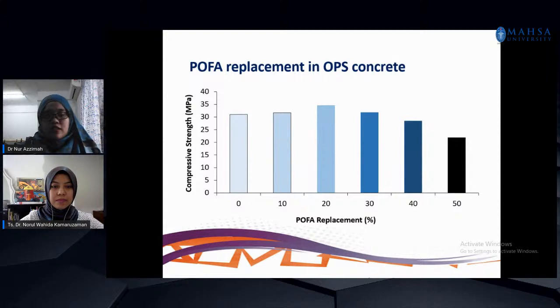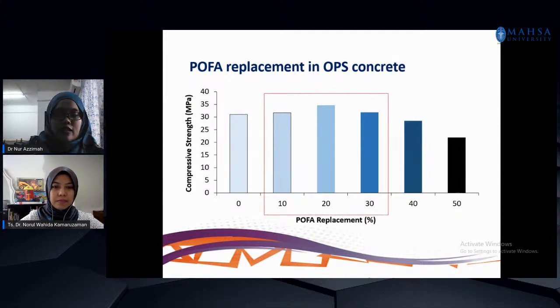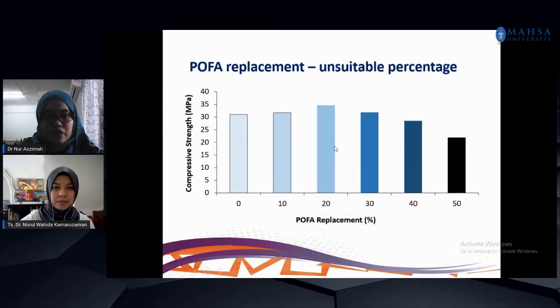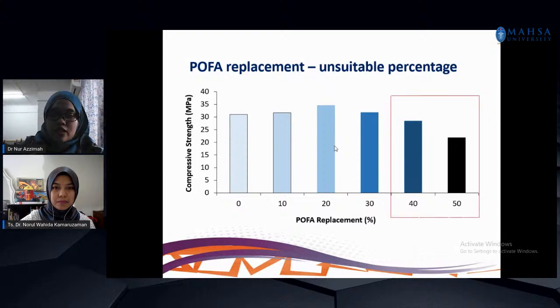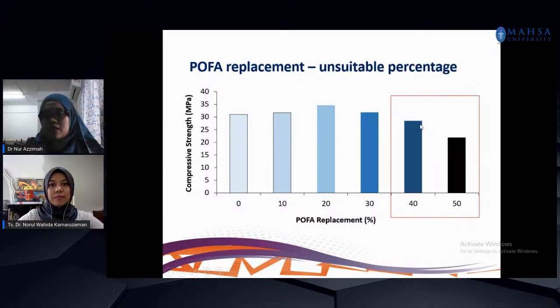From our findings, we figure out that these three have the highest result, which is from 10% to 30%. We do from 0 to 50%. Zero means the OPS concrete without any POFA, and 50% is up to 50% replacement. So we can see that these three produce the highest strength. And at 40% and 50%, the data shows the strength decreased.